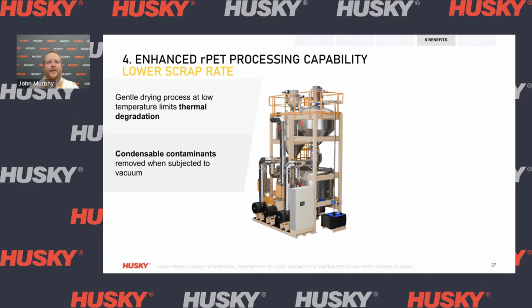In addition, condensable contaminants are removed when material is subjected to minus 850 millibar vacuum. Instead of these contaminants getting into the process air of the dryer, they are evaporated out along with the water. There is no additional maintenance required due to condensable contaminant generation. The vacuum drying system is equipped with 4 process filters, 1 for each hopper, resulting in 4 times the filtration capacity of a traditional desiccant dryer to handle that higher level of dust that we can see when processing rPET material.